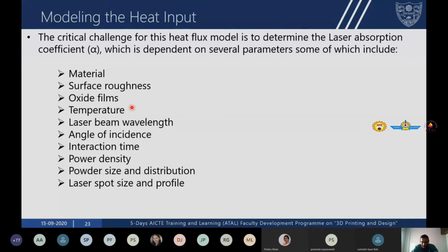You have Nd:YAG lasers which have a different wavelength compared to CO2 lasers. It also depends on the angle of incidence of the laser beam, the interaction time between the laser and the powder particles, the power density, which can be defined as power divided by scan speed times diameter, the particle size and distribution of the powder particles, and the laser spot size and profile. All these factors affect the laser absorption coefficient alpha, and you can see that this parameter is needed for the computational modeling work, and it is a very complex parameter to obtain experimentally.